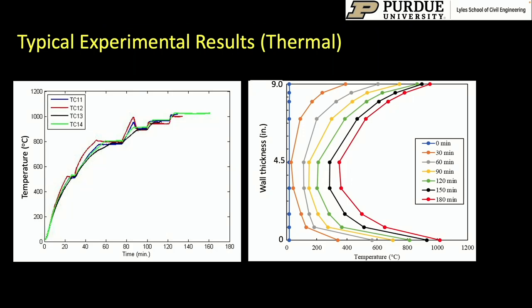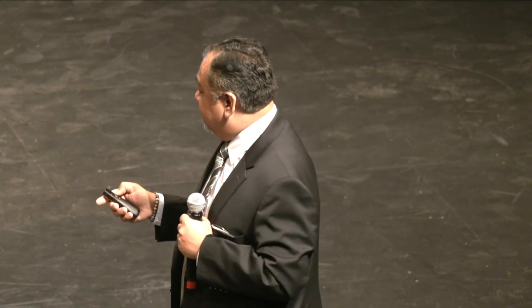The typical experiment results, I'm showing you some of the thermal results. The surface temperature of the steel reaches about 1,000 degrees centigrade, which is what you'd want to see in a fire test. But the thermal gradient through that composite section is shown here. While the steel surface temperatures are about 1,000, towards the center of the wall, the temperatures are much lower. And this was only a 9-inch thick wall. That's not very thick. It's actually a 1/3 scale model representation of the wall.